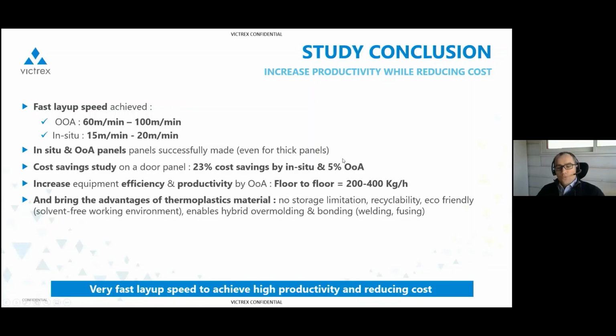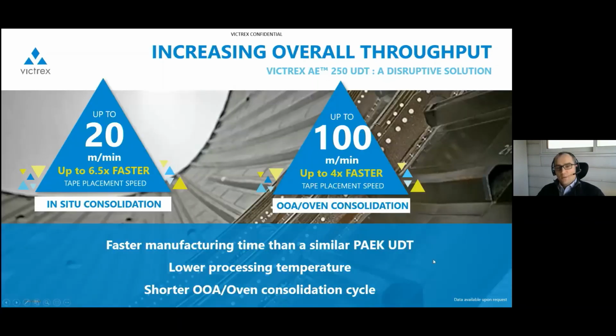So to wrap this up, if you have to keep in mind two data points in terms of achieving high speed: for in-situ, you can achieve close to 20 meters per minute, and for out-of-autoclave or oven consolidation, you can achieve up to 100 meters per minute, which is quite high compared to other materials. And then, lower processing temperature and a shorter out-of-autoclave oven consolidation cycle. This is not the objective of this presentation either, but for the consolidation cycle, if there is one, using LMPAEK you can reduce it.